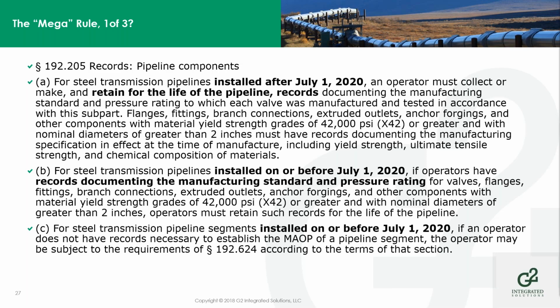Records again for pipeline components after July 1, collect or make or retain for the life of the pipeline. Those records documenting the manufacturing standards that the devices were built to for things greater than 2 inches and with yield strengths of 42,000 PSI or X42 pipe. For steel transmission lines installed before July 1st, 2020, if you have records documenting the manufacturing standard, you must retain those records for the life of the pipeline. And then again, if you do not have records to document that, you must follow 624.